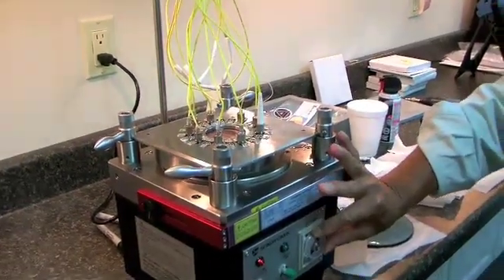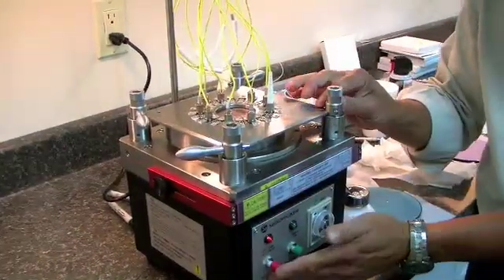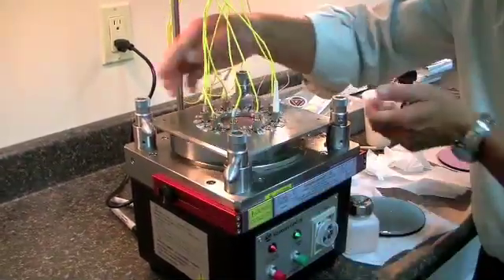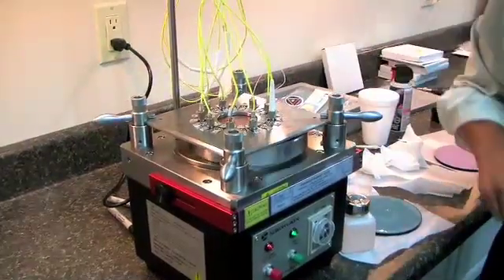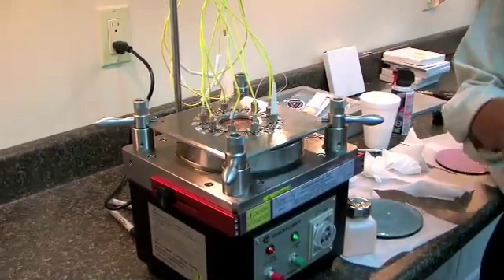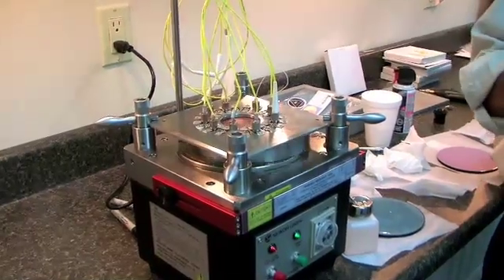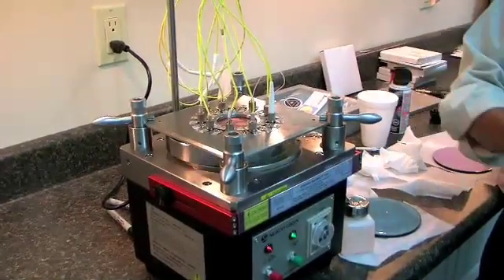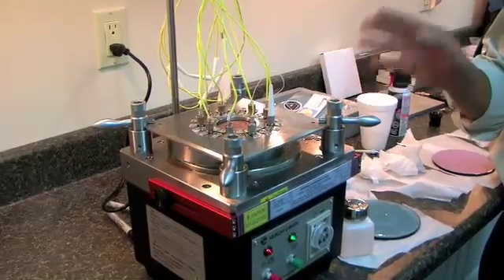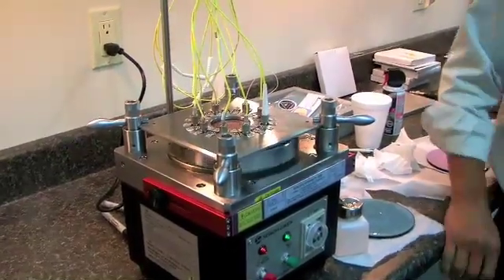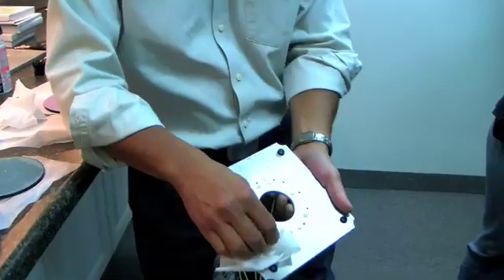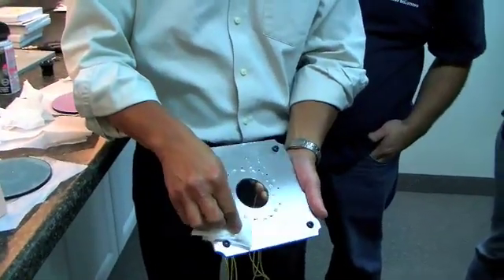Now you'll set your timer for 45 seconds. You'll turn the machine on first, and then as it's turning, then you put the pressure on. Two at a time. The snap crackle sound that you hear are air bubbles underneath the film. Totally safe. Nothing's going wrong. That's because we didn't have a roller to burp out the bubbles under the film to the rubber pad. So those are common sounds that you hear. Nothing's breaking. It's just air bubbles snapping. That's grease on the plate. Clean it again. See how the water is white now? That means we're actually polishing the ceramic and the fiber together.